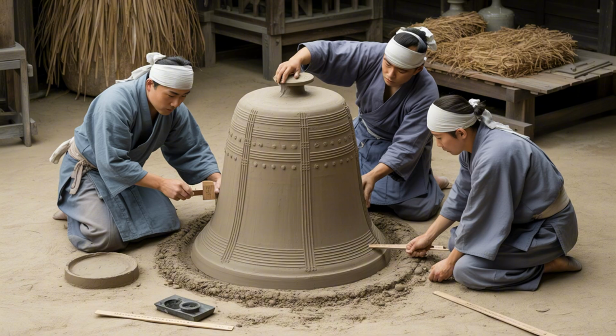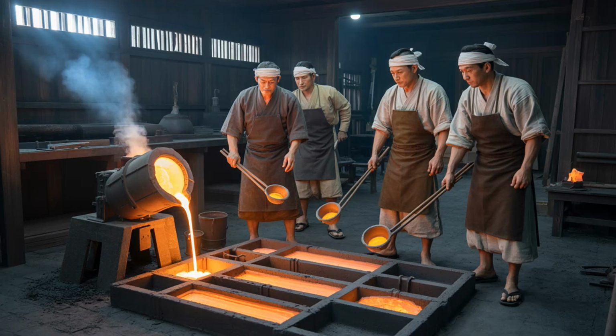The risers were even more clever. These were extra chambers connected to the mold that served as reservoirs of molten bronze. As the bronze in the mold cooled and contracted slightly, the risers would feed additional metal to compensate for the shrinkage. Without risers, bells would have sunken areas or internal voids that would ruin their tone. It was like having a backup fuel tank for your casting.